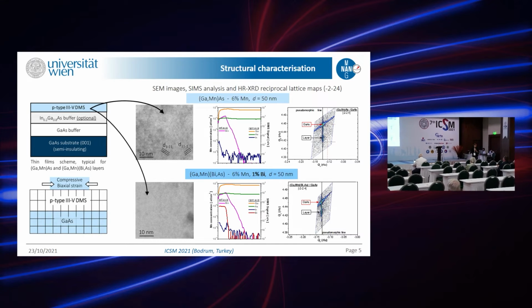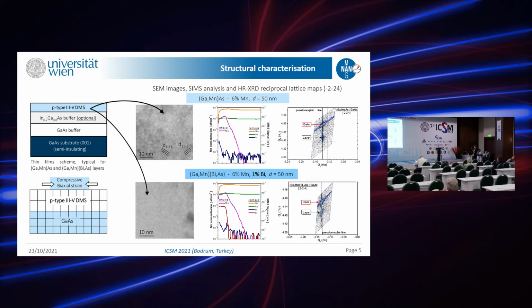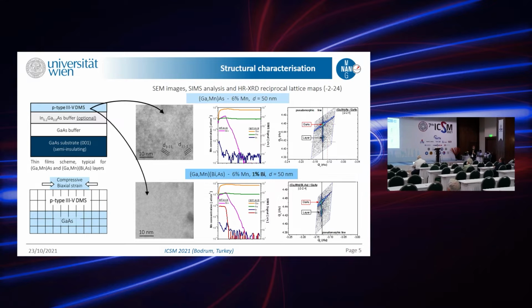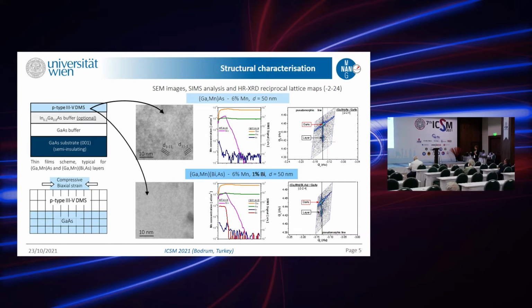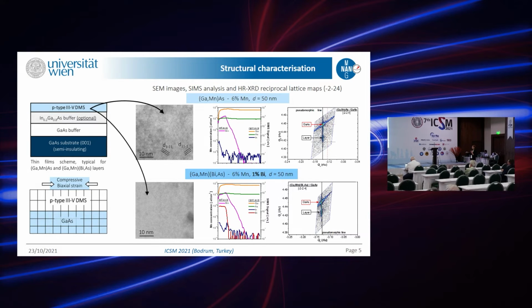Also, SIMS showed that we have a signal from manganese and bismuth throughout the first 50 nanometers, where it is supposed to be, while gallium arsenide is throughout all the layers. And reciprocal lattice maps show that we have nice strong peaks from the substrate and layer. Hence, in the end, we can say all our samples have good crystalline quality. We can proceed further to characterization.